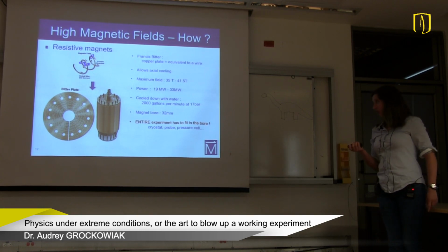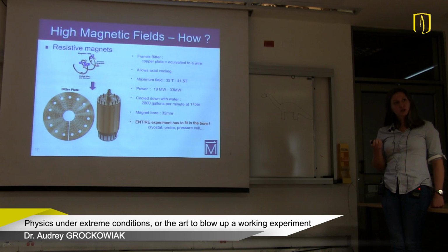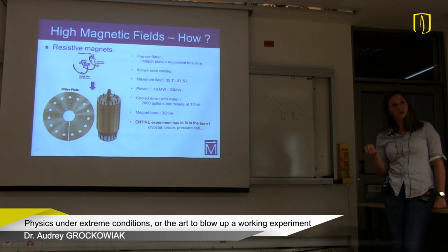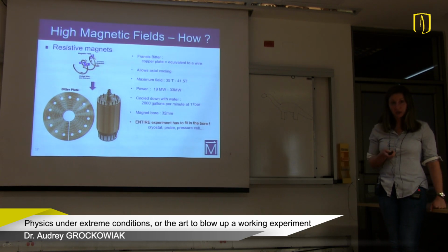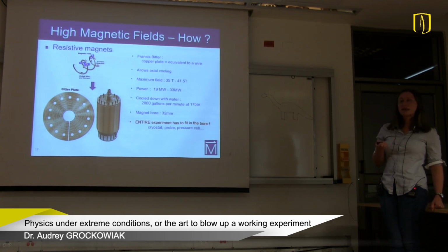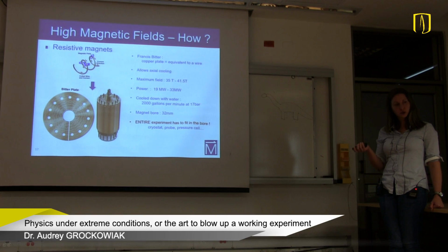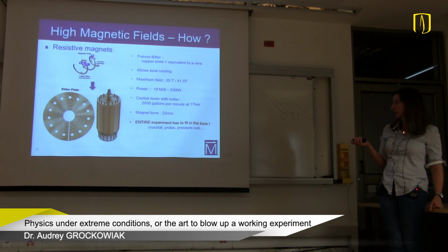And you have to be able to put a huge amount of current inside those coils to get to higher magnetic fields. The problem is that the more current you put in the material, the more you're going to warm the material. So if you want to have a working magnet, or a magnet that lasts for a very long time, you need to find a way to cool down your magnet. And this is what Francis Bitter developed. So this is called the Bitter plate. It's basically copper or an alloy of copper. And here you see different slits and holes. And those holes are actually used to push some water through the coil to cool it down when the magnet is working.